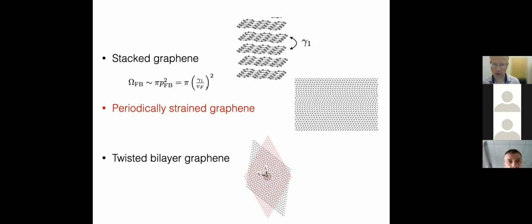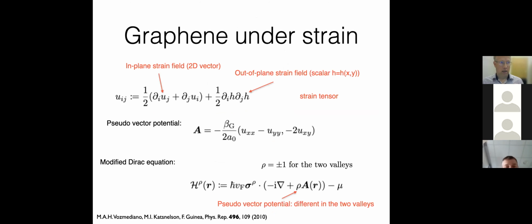Now, we have also considered other types of flat bands. The next topic is periodically strained graphene, and how does this work? You can shift the atoms in the lattice adiabatically, and if the shifts are small compared to the average lattice, you can treat them with adiabatic theory, starting from the ordinary Bloch theorem of periodic lattices and studying these shifts as perturbations. In this case, what you study is the strain field, which may consist of in-plane and out-of-plane strains, and from those you construct a pseudo-vector potential.